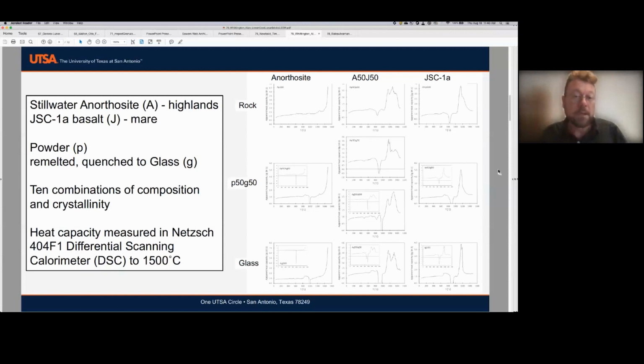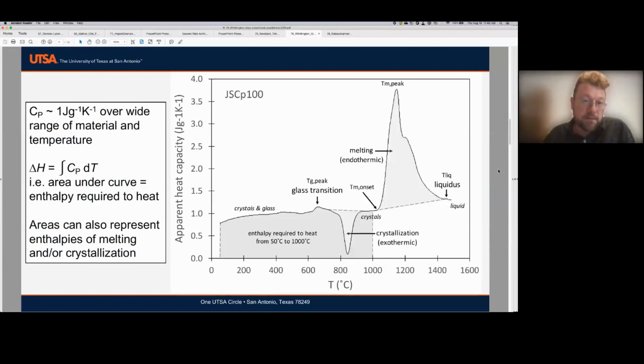Next slide, please. And what we did was we measured the heat capacity using differential scanning calorimetry. So you'll see several graphs that look like this. I just need to spend a minute to explain what these graphs mean. The x-axis, of course, is temperature, so that's easy, but the y-axis is apparent heat capacity. So this is basically what the calorimeter thinks the heat capacity of the material is. Now, the actual heat capacity of these materials is about 1 joule per gram per Kelvin over a wide range of composition and temperature. The heat capacity increases at higher temperature, and it's higher for liquids than it is for crystals, for example.